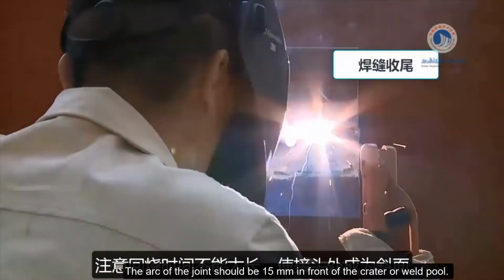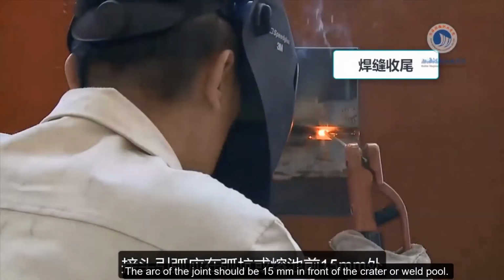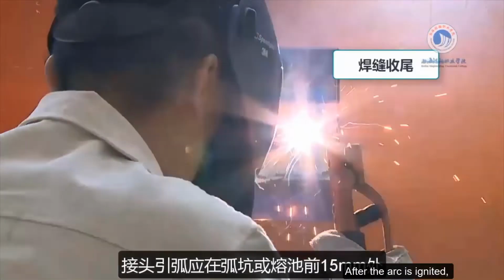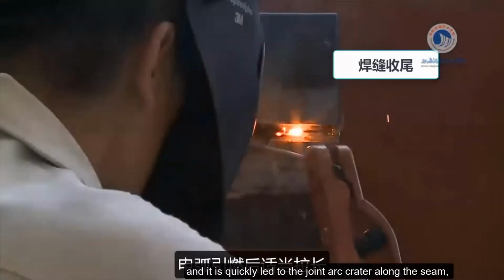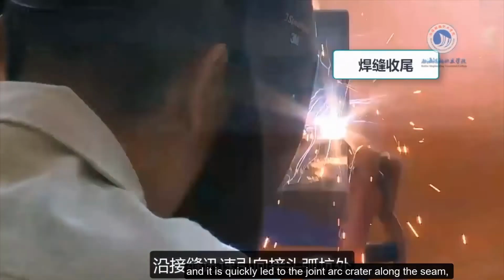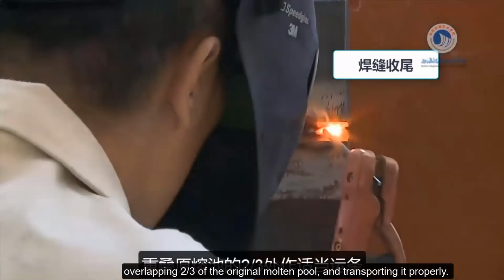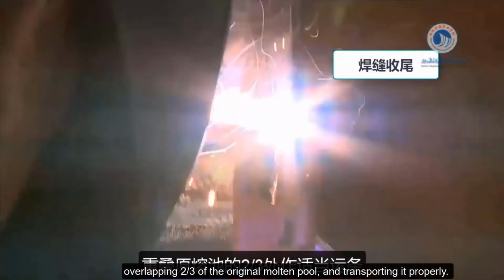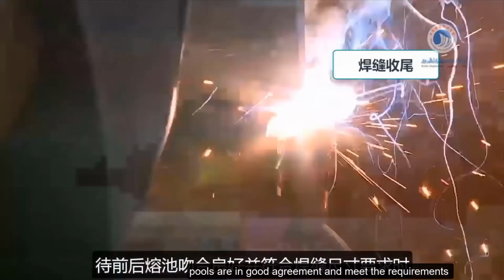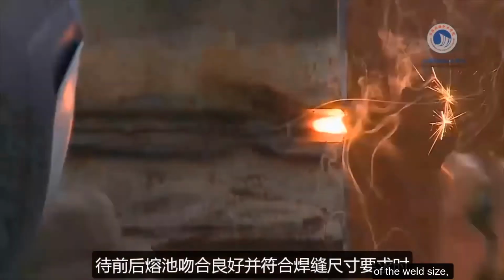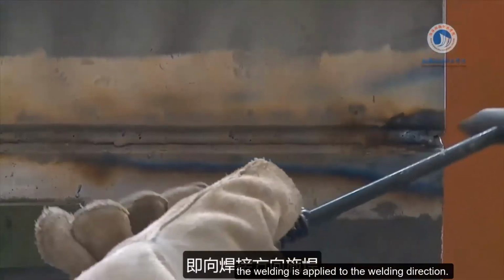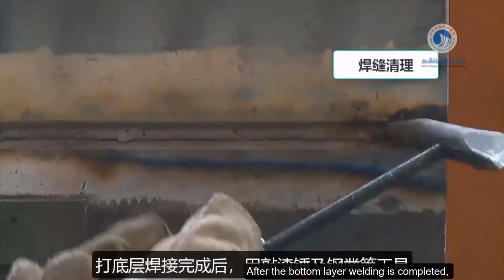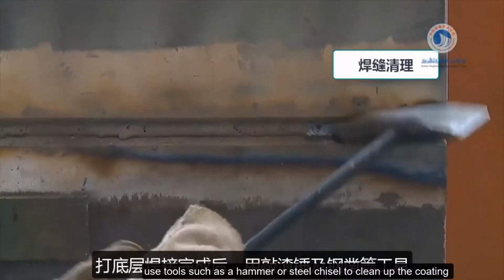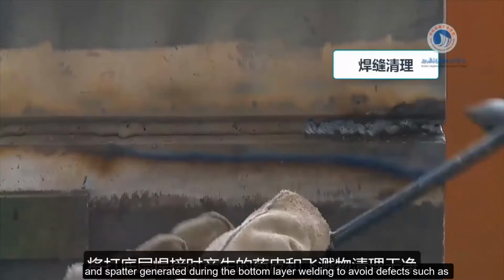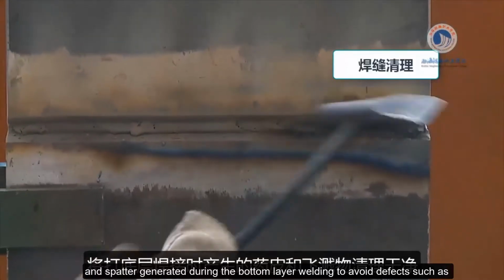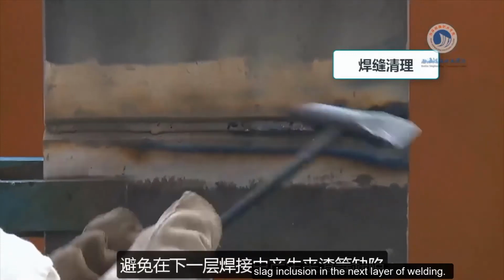The arc of the joint should be 15 mm in front of the crater or weld pool. After the arc is ignited, it is properly elongated, and it is quickly led to the joint arc crater along the seam, overlapping 2/3 of the original molten pool, and transporting it properly. When the front and rear molten pools are in good agreement and meet the requirements of the weld size, the welding is applied to the welding direction. After the bottom layer welding is completed, use tools such as a hammer or steel chisel to clean up the coating and spatter generated during the bottom layer welding to avoid defects such as slag inclusion in the next layer of welding.